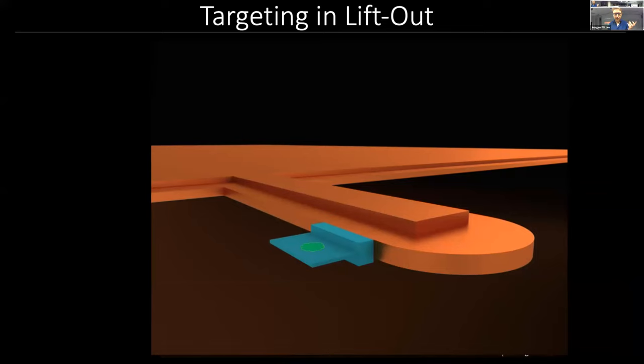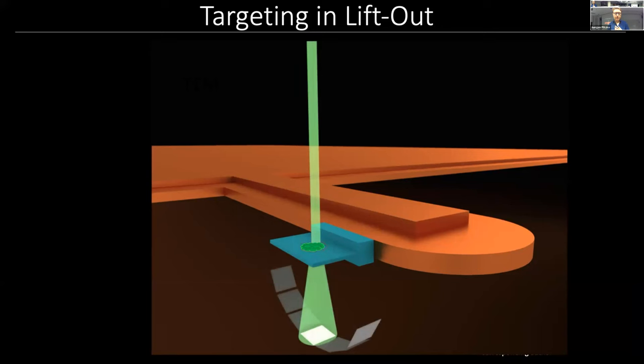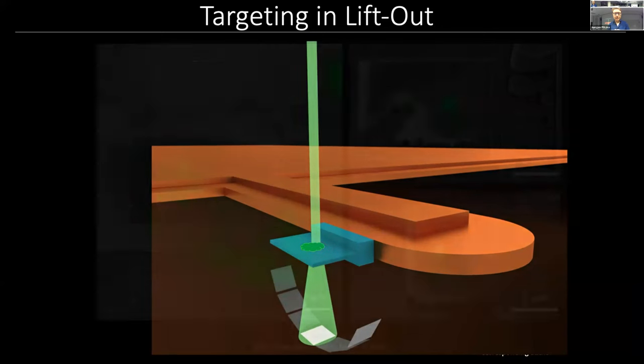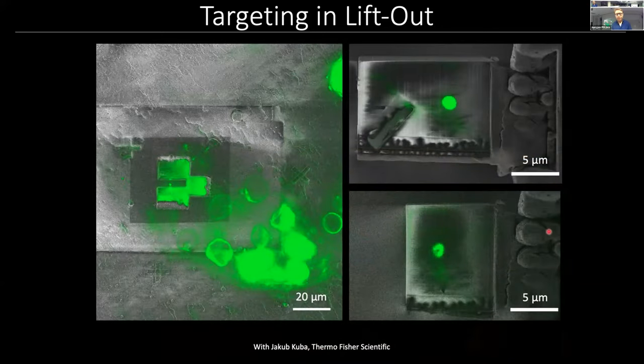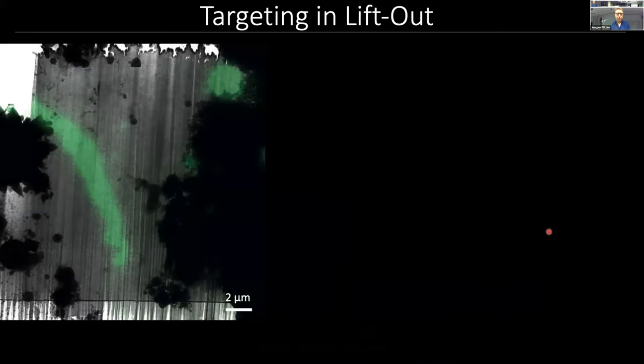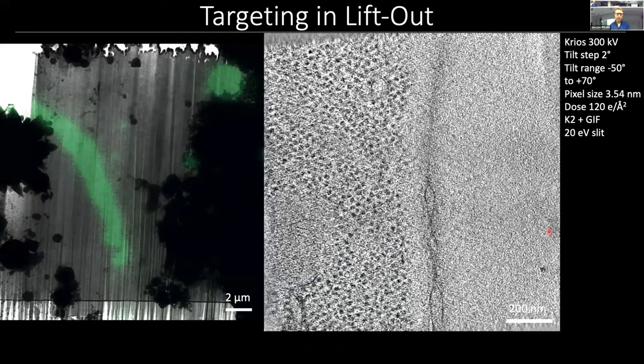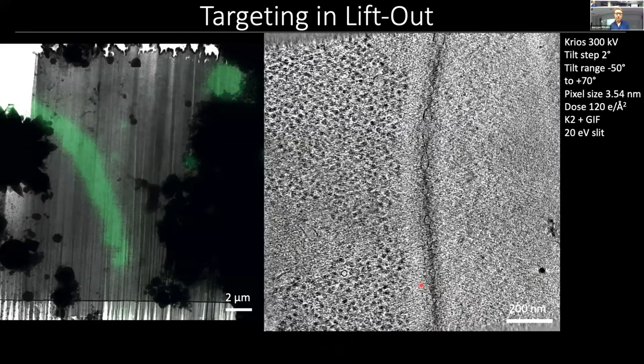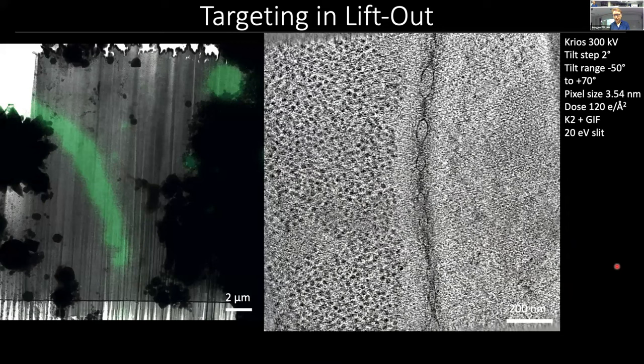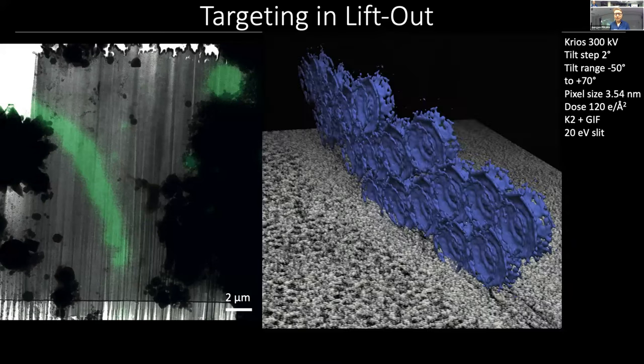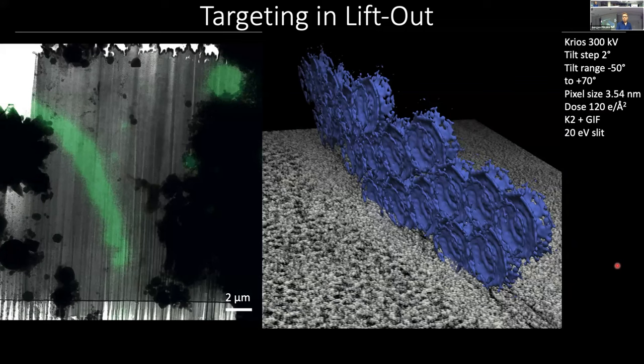Now, the other thing is that with the integrated light microscope, what you can then do is guide your data collection by a fluorescent spot inside your tissue, and here just shown for a phase separated compartment, which we would never be able to target by scanning electron microscopy simply because you don't get any contrast for it. And this then allows you to target features just like the nuclear envelope inside the Drosophila egg chamber. And again, showing that these are really packed and quite specific for the germline nucleus.